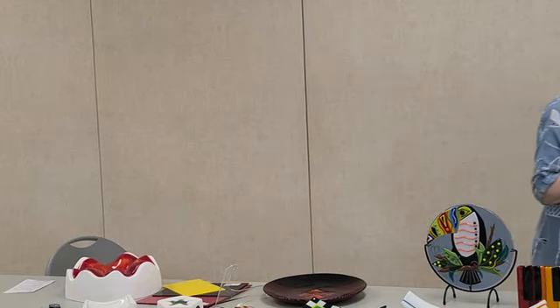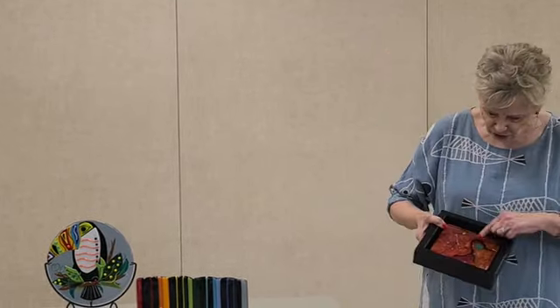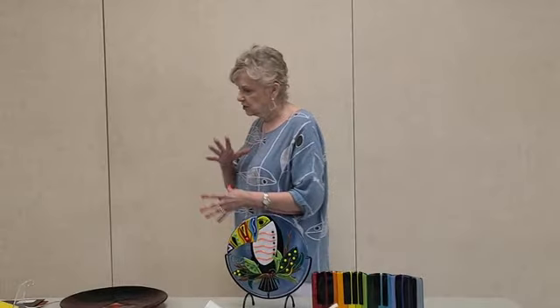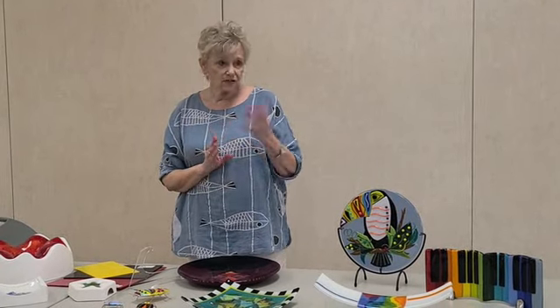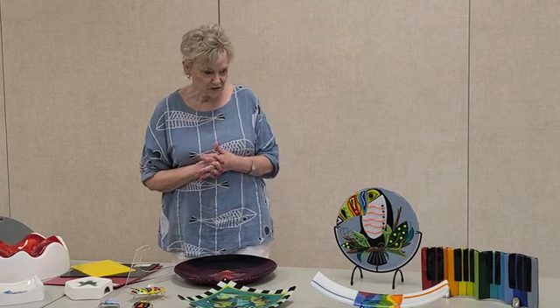Yeah. And this was so many layers of glass and so many different pieces and so many places for glass to get trapped. Just like in the jewelry pieces, you're just creating bubbles. You want to pass that around? I'll show you where they are. See that kind of S? There's some down here around the S. And I know in my schedule for that, there was a long bubble squeeze. It's called a bubble squeeze. There was a long section in there for that air to all get out from under because the glass was just piles and piles. And so there's still bubbles. That's just the nature of it, it's artistry.